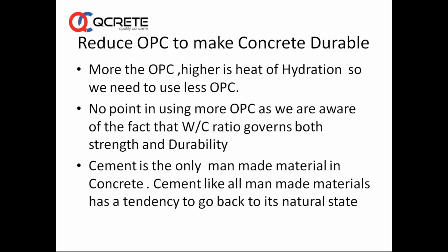The situation now is that the same 400, 410 or 420 kg cement content will give a strength of about M40 or M45, thanks to the usage of enhanced or high performance admixtures. On the other hand, the same M25 can be done with 300 or 320 kg mixes. So this is the current situation where, due to the availability of high performance admixtures, the cement contents can be easily reduced, and there is no point in using a high amount of OPC. We have a lot of data showing that with lower OPC and lower water cement ratio, you can get higher strength. No point in using higher OPC.